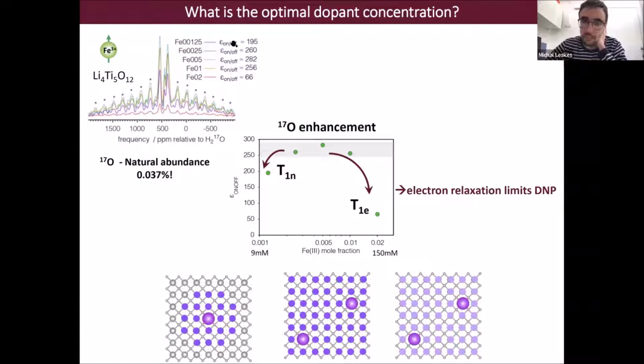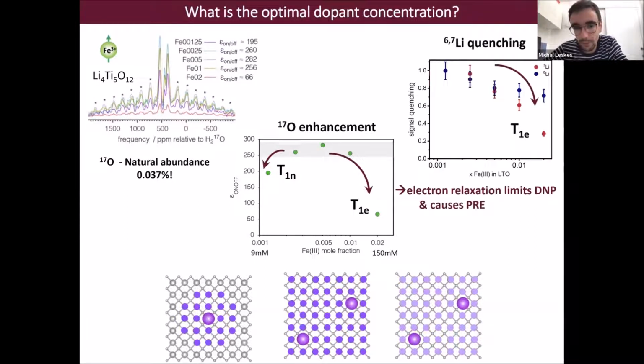So back to the question, what is the optimum concentration for sensitivity gains? From this figure alone, one would think we want to be at the highest possible concentration before we drop here due to reduced electron relaxation time. However, this figure does not show another important aspect that we have to keep in mind, which is the signal quenching. Due to the strong paramagnetic relaxation enhancement, as we increase the amount of metal ions, we get shorter and shorter T2, to a point that some nuclei very close to the paramagnetic center we can no longer observe due to the instrumental limitation of our dead times after the pulse.